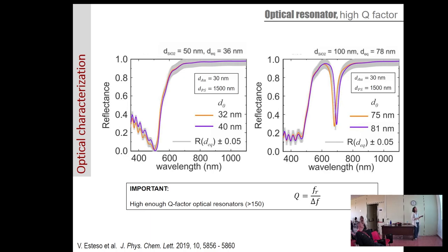In these two examples, I just want to show you that we need high enough quality factors in our optical resonators, about 150, which is something easy to have. To give you an idea of what could happen, this is the reflectance of a system at equilibrium. It is displayed with this gray line, and it is thick because I'm considering a 5% error that could arise from some misalignment, roughness, or some experimental issue.